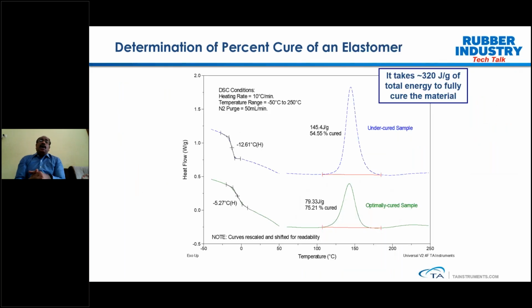Now I can show how DSC is helpful to understand the percentage of cure. Here I presented two curves, so you can see the solid green line curve, which is of optimal cure condition. So how do you understand whether the polymer is completely cured or not, or undercured? You can use DSC as a technique to determine this aspect. There are two ways you can see. One is by looking at the glass transition temperature of a cured material.